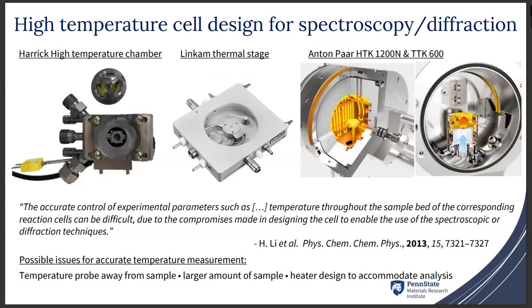One of the main things that happens in the drift of temperature comes from the fact that the temperature probe is often away from the sample, because we cannot do the spectroscopy and have the temperature probe where we are doing the spectroscopy. The amount of sample we are using is larger, often tens to hundreds of milligrams, which leads to differences of temperature at different places in your sample, and there's also the design of the heater in order to accommodate the spectroscopy or diffraction.